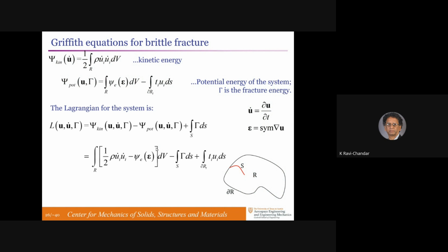So the idea behind the phase field method is to write the Lagrangian for the system, consisting of kinetic and potential energies, and include in it the fracture energy to reinforce Griffith. The idea is that this is over the set of points that form the crack. And that is what makes it difficult to handle. You cannot do this for an arbitrarily unspecified crack path. The Euler-Lagrange equations, I don't even know what they would look like to write.